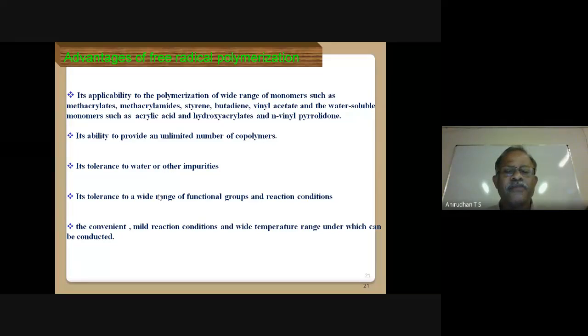Its ability to provide an unlimited number of copolymers you can identify. Then you can utilize as a graft monomer methacrylate, methacrylamide, styrene, butadiene, vinyl acetate. Just like vinyl, even N-vinyl pyrrolidone can be utilized as a monomer to graft this backbone of the chain. Then its tolerance to water or other impurities, and its tolerance to a wide range of functional groups. You can introduce any functional group, even amino group, carboxylic group, sulfonyl group, acetyl group. Like this, many different types of ligands you can introduce in your cellulose after modification through free radical polymerization. So once you utilize free radical polymerization, there is no restriction. You can utilize any ligands to introduce in your material.